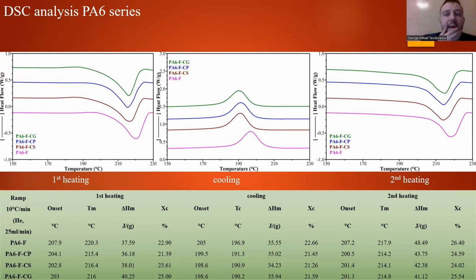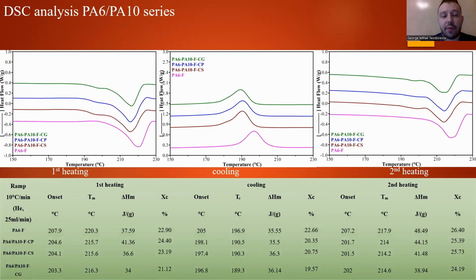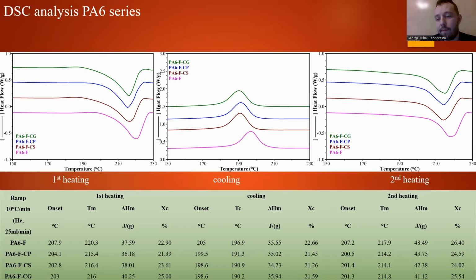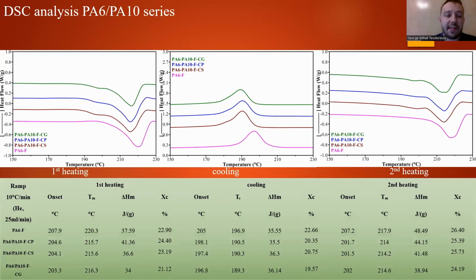Now, the results for DSC analysis indicate differences between the composites where the melting and the crystallization temperatures decrease by a maximum of 5 degrees for the composites containing treated ash compared to the control composite PA6F in both series. And these decreases may indicate a plasticizing effect of the agents used to treat the fly ash surface, as the crystallinity values correlate well with the modulus and stiffness results from DMA analysis, indicating more flexibility for the ash-treated composites.